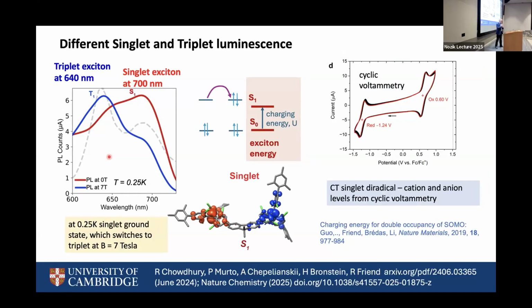or anti-parallel. So the key experiment, which is courtesy of Alexei Chepelyansky in Paris at Orsay, he has a dilution fridge, and we don't have to pay the electricity bill for running it. So we're down at 1/4 of a Kelvin, looking at the luminescence. Down at 1/4 of a Kelvin, the two electrons are antiferromagnetic. We've got an antiferromagnetic exchange, and the luminescence comes out at 700 nanometers. If I put a magnetic field on, this is overkill, it was 7 Tesla, the superconducting magnet there as well, the magnetic field will swing the two spins to be parallel, and we force it to be a triplet.